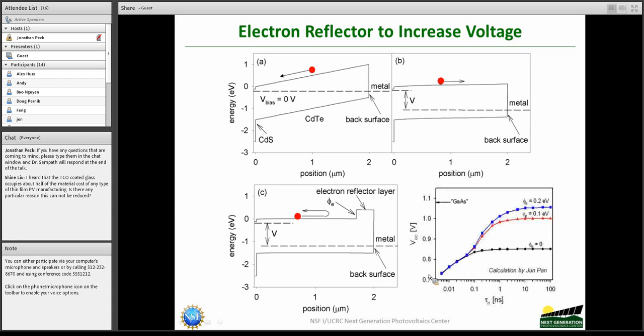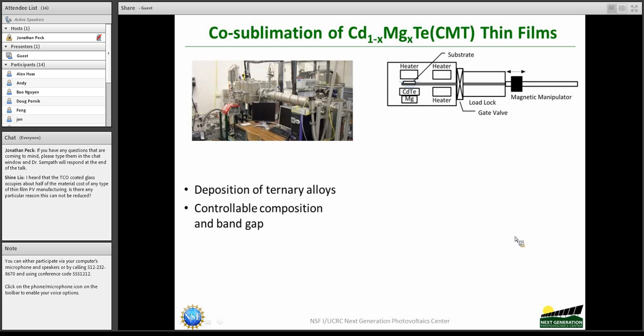And all the modeling suggests that we should be able to pick up a fairly significant amount of voltage gain by putting this layer at the back. And the predictions are that we can go from our current 850 millivolts to somewhere in the neighborhood of 1.1 volt. Now, this research is well underway. We haven't seen these improvements yet, only smaller improvements with smaller thicknesses, and we're optimizing the process so that we realize this full voltage gain that is predicted by theory.